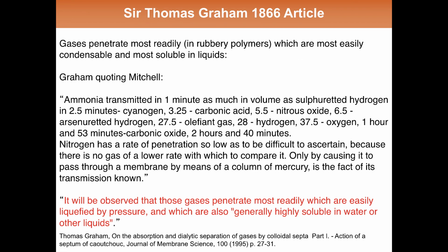And he went back to the work of Mitchell, where Mitchell noted that different gases had transmitted at different rates through the same membrane. And Graham noted that it will be observed in Mitchell's results that those gases penetrate most readily which are easily liquefied by pressure, and which are also generally highly soluble in water or other liquids.